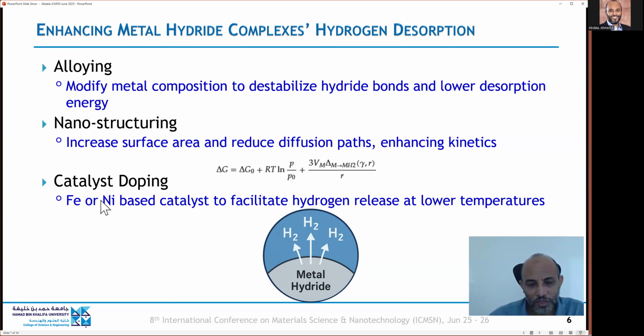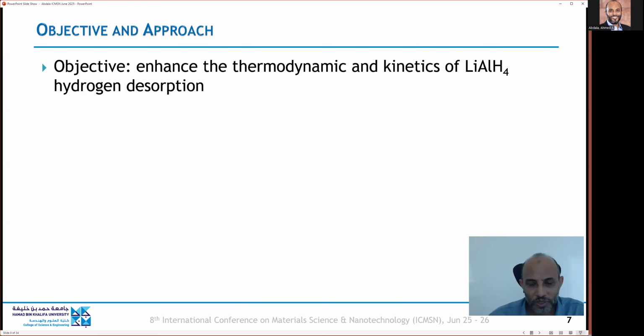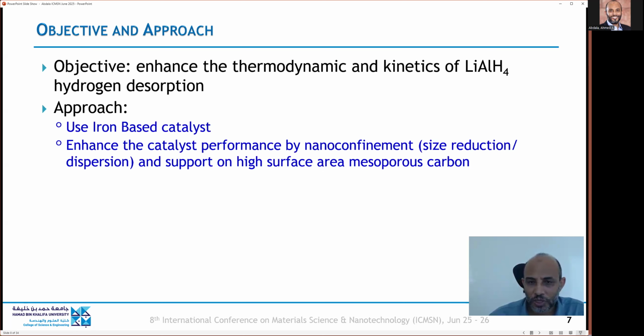Another approach is to dope the metal hydride with a catalyst, usually an iron or nickel-based transition metal catalyst, which facilitates the hydrogen release at low temperature by interacting with the metal and the hydrogen. So it reduces the metal-hydrogen bond strength, which makes it easier to dehydrogenate. So in this research, we aim to enhance the thermodynamics and kinetics of lithium aluminum hydride for the hydrogen desorption step. The approach is that we combine the use of an iron-based catalyst and enhance the catalyst performance by nanostructuring. So we do a nanoconfinement to reduce the size of the catalyst particles and improve their dispersion. And also we increase the surface area by supporting the catalyst on a mesoporous carbon.